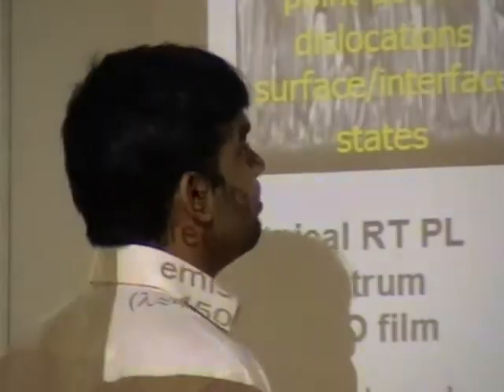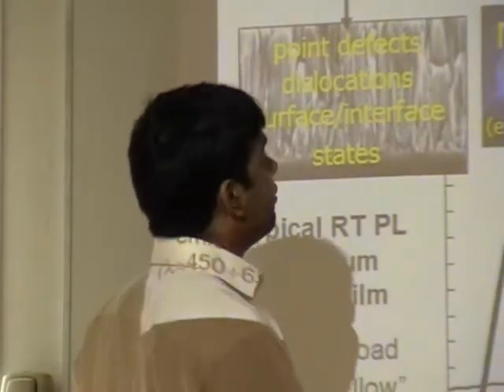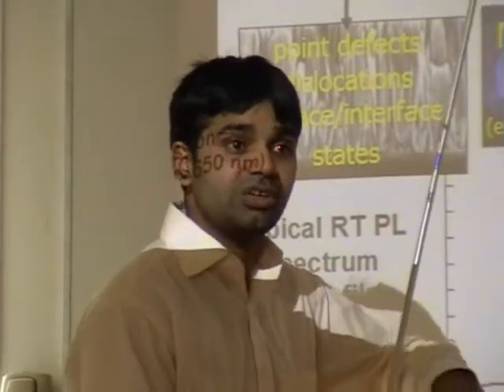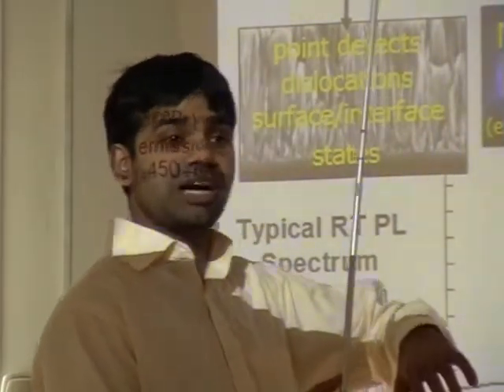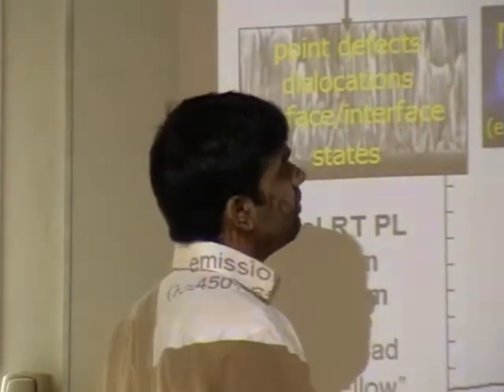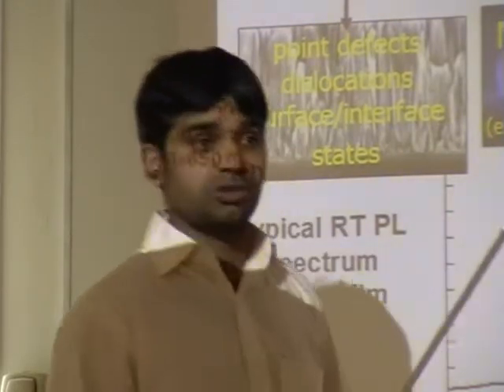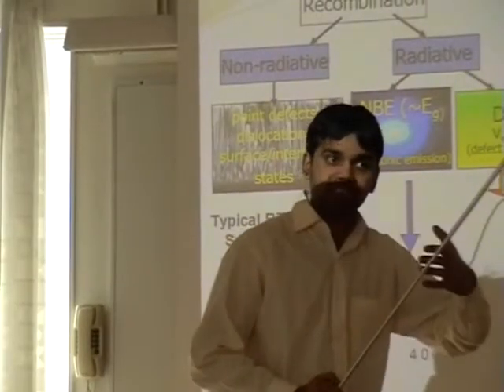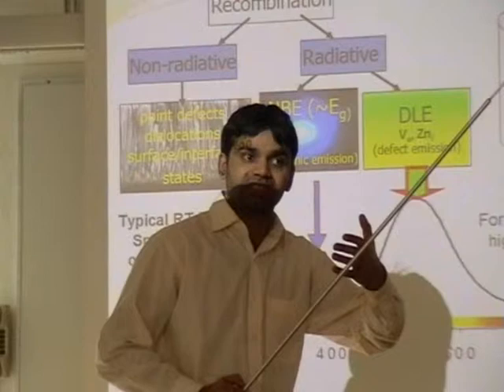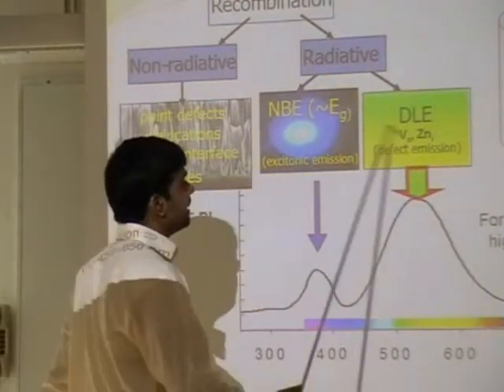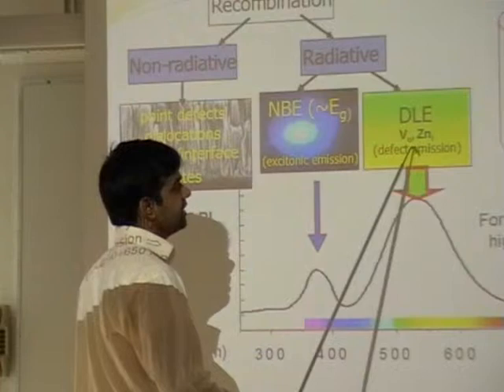At low temperature, near band edge emission is very difficult because the efficiency of the radiative emission is very low, that is 10 raised to power minus 1 to 10 raised to power minus 3. As for deep level emission, there is still controversy. Maybe it is due to some defect or impurity present in the zinc oxide. And thus the deep level emission is a defect emission.